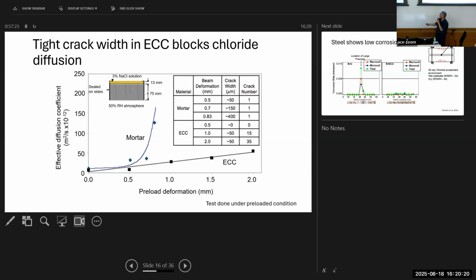Now, when we plot the diffusion coefficient, so we put a specimen under a concentrated sodium chloride solution and measure how far the chloride ion penetrates into the specimen over time, we deduce this effective diffusion coefficient and plot it against the preload deformation. For the case of the ECC, we saw a linear increase, and this is reflecting the increase in the number of cracks as we increase deformation. But in the case of the mortar, we see a highly nonlinear, accelerating increase in the diffusion coefficient. So this is telling us that it's very dangerous to have crack widths that are large. It actually rapidly increases the diffusion coefficient and causes corrosion in a much shorter time compared to that of the ECC.